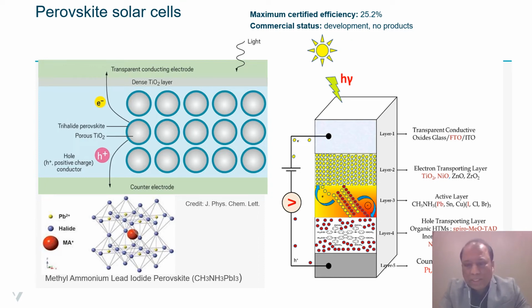So how is it used in a solar cell? Yes, of course you have an absorption layer. Absorption is the important thing as far as solar cells are concerned. The material must have good absorption, so you have to absorb the photons. So light passes through the transparent electrode, the green one here, so what happens? It goes through the photosensitive perovskite material here, and it stimulates excitations called electron-hole pairs. And what happens? The electron goes through the dense TiO2 layer and to the electrode, whereas the hole goes through what we call the hole transport layer and to the counter electrode.